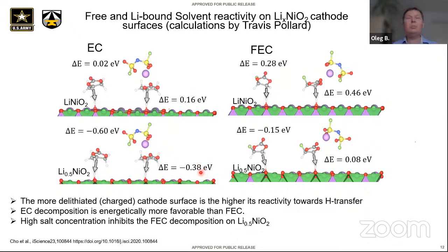So the stabilization, I've seen initial papers suggesting a couple of eV due to that. We do observe for this type of reaction, it's only 0.2 eV, but that might be enough to extend a little bit further your charging range and allow more capacity extracted out of the cathode, right? So what happens if we fluorinate? If we fluorinate EC, make FEC, then that's a fluorine here. Then extracting a proton becomes less favorable.